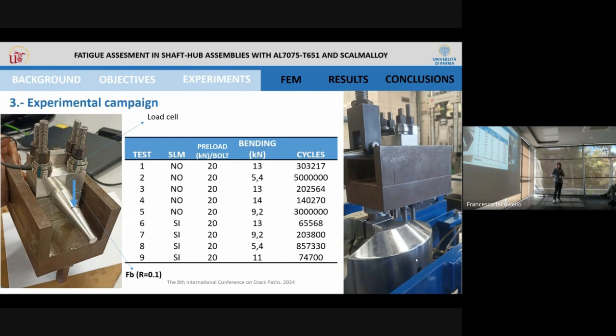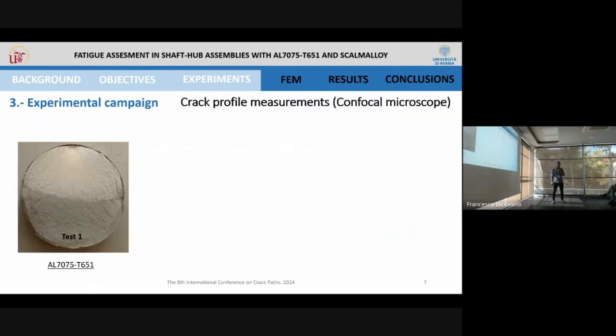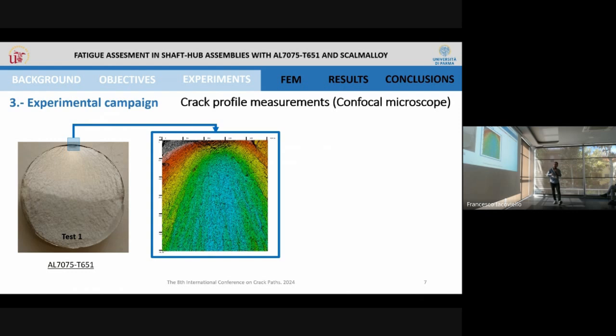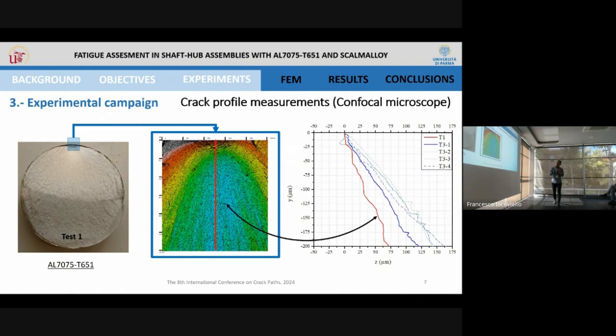And after all these tests, we analyzed the fracture surfaces. For this, we used a confocal microscope. We located the initiation point, and at this point we obtained the topography of the surface in order to draw some different lines to obtain the crack initial path, like the one shown here. These are some measurements for 2 test specimens made of aluminum 7075. The orientations range between 15 and 45 degrees, up to a length of 50 microns. The results will be compared later on with the model.